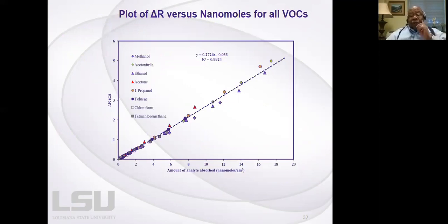And indeed, that's true. Notice that at lower concentrations, it fits much better. At higher concentrations, you get bigger deviation, which is what you would expect for ideal gas behavior, right? As you get to higher concentrations, these gases interact with each other, and therefore you get deviations from ideality. At lower concentrations, they do not interact with each other, so you get a better fit to ideal gas behavior. And this is simply a plot of delta R versus nanomoles for all of these volatile organic gases. And notice that you have an array of gases. We have methanol, acetonitrile, ethanol, acetone, propanol, toluene, which is benzene-like, chloroform, tetrachloromethane.